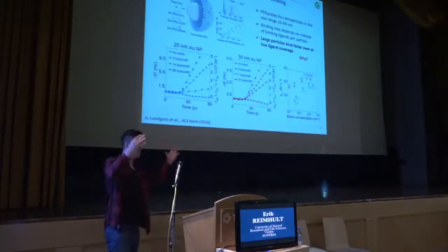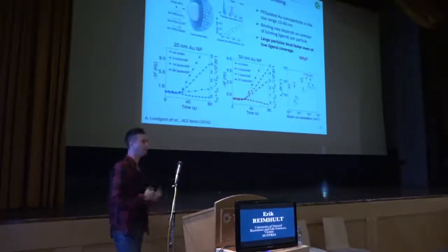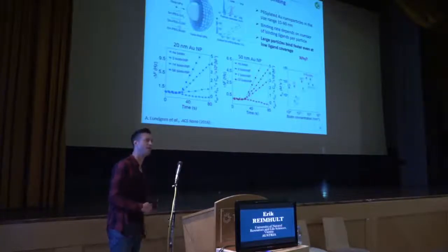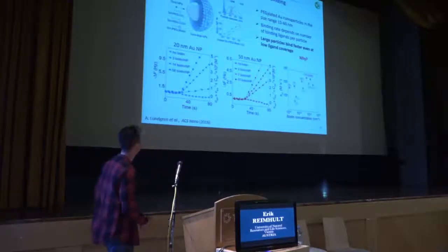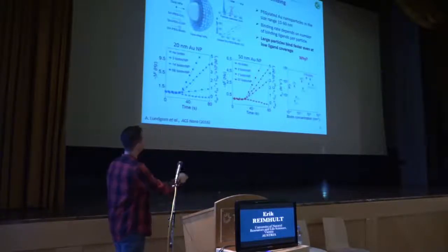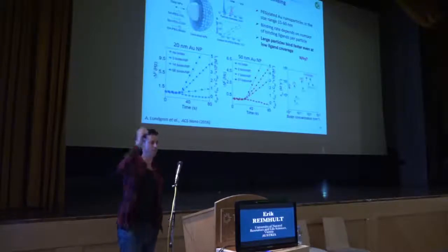Then we add a functionality, biotin, that binds to streptavidin, I guess most of you know. So it has a very high affinity, and we can measure the K-on rate of that binding under controlled conditions where we should have reaction-limited binding. And what we observe is that, contrary to what you should have if this is purely kinetically limited, the size matters for the K-on rate.